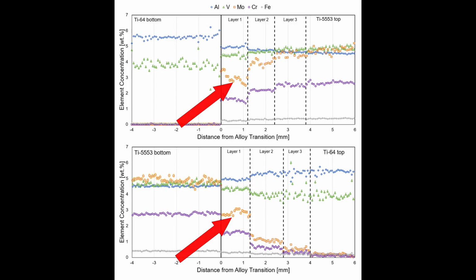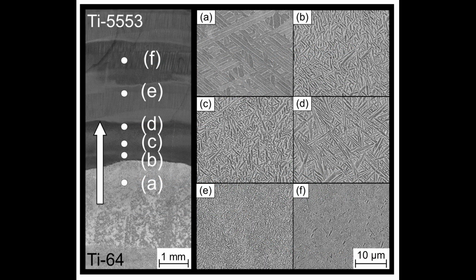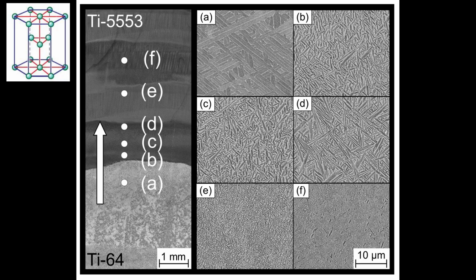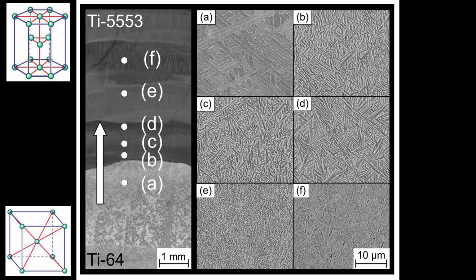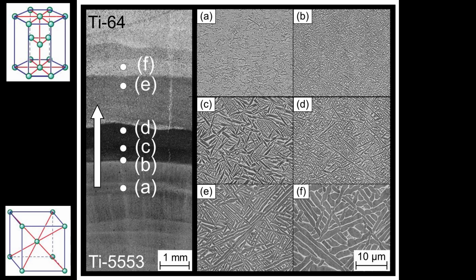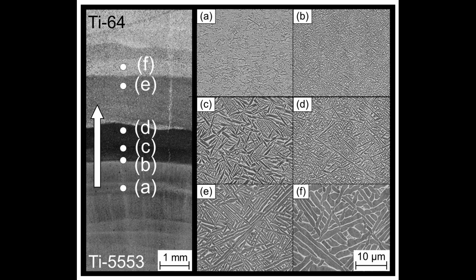In titanium alloys, such as those used in this study, the microstructure consists of the hexagonal alpha phase and the cubic beta phase, woven together on a nanometer scale. The scale of this interweaving determines the mechanical properties. In particular, a finer microstructure results in a higher yield stress of the material. And, since the balance of the two phases is determined by the alloy chemistry, the stepwise alloy mixing in the alloy-alloy composite transition region produces abrupt changes in the microstructure.